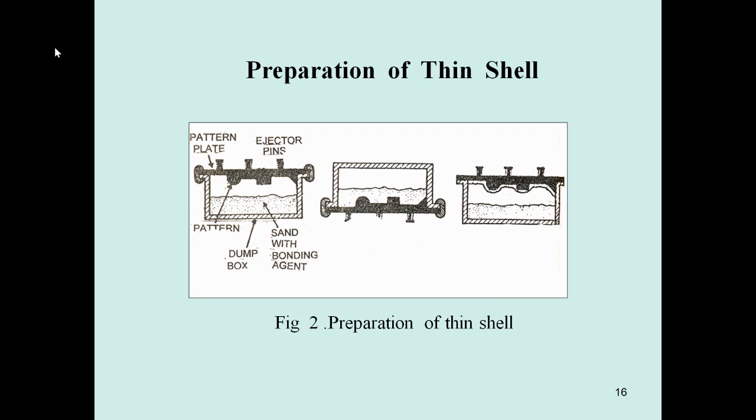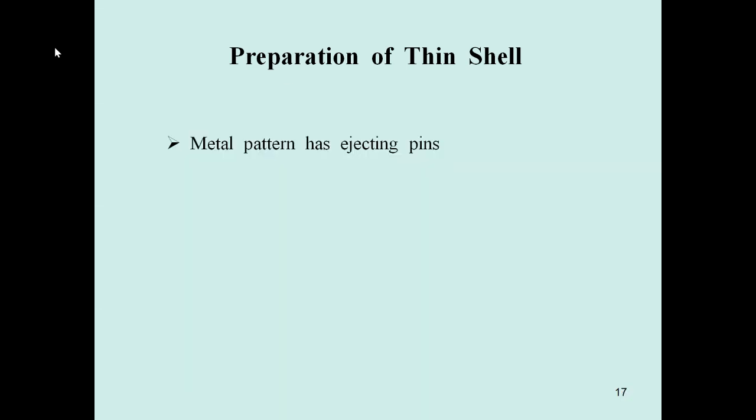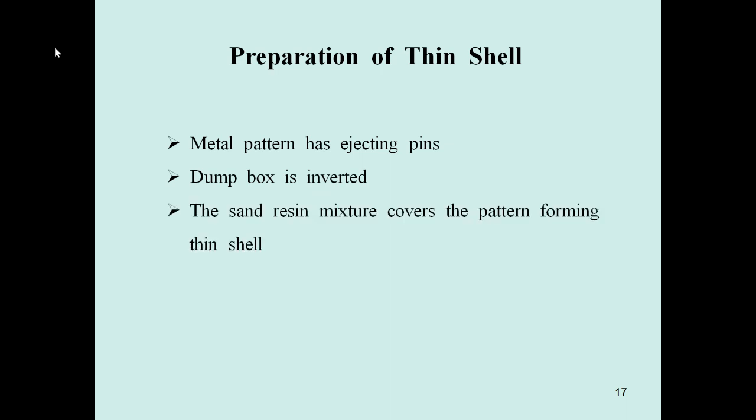The dump box is inverted so that the sand resin mixture covers the pattern. After about 30 seconds, the resin cures and the shell is formed.